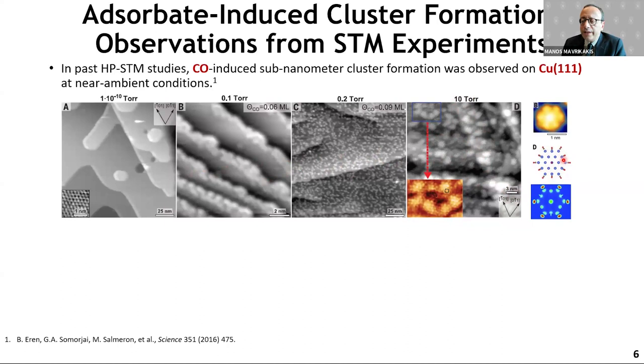This is like a two-dimensional pancake of copper atoms, where if you count the blue atoms representing copper atoms, is 19. And then you see these CO molecules decorating the circumferential copper atoms, and then you have one CO molecule at the center of the copper pancake as well. Of course, you have clusters, different number of copper atoms, but the most stable one is this one with 19, it turns out, per experiments done in Somorjai's laboratory.